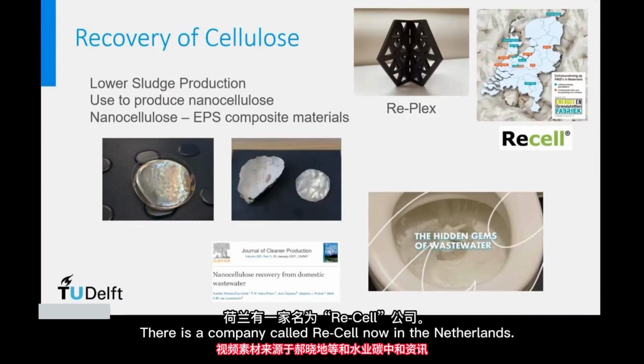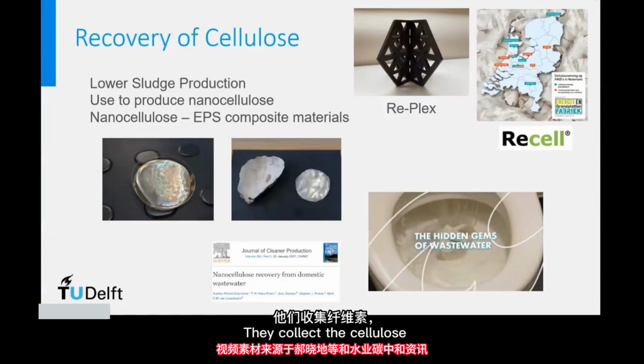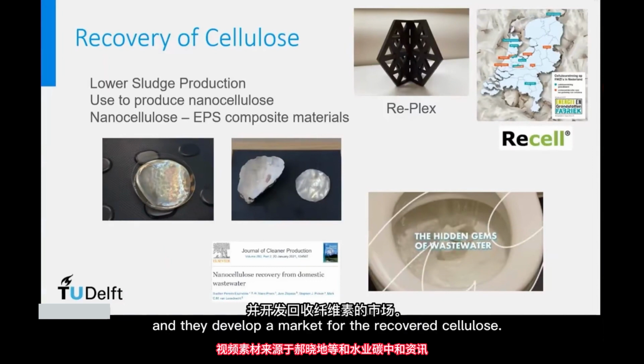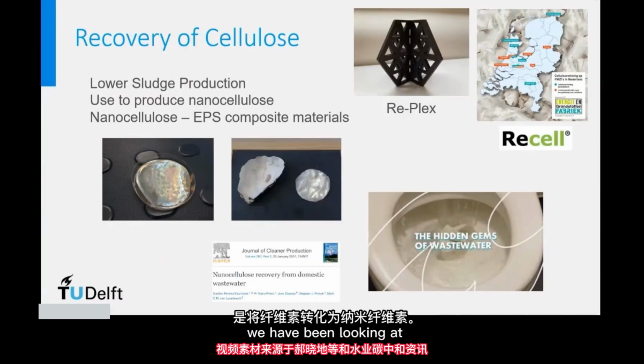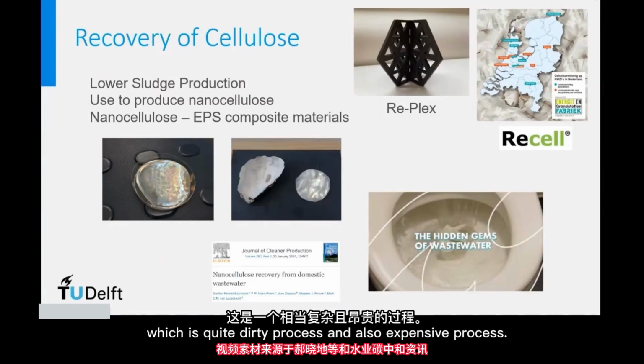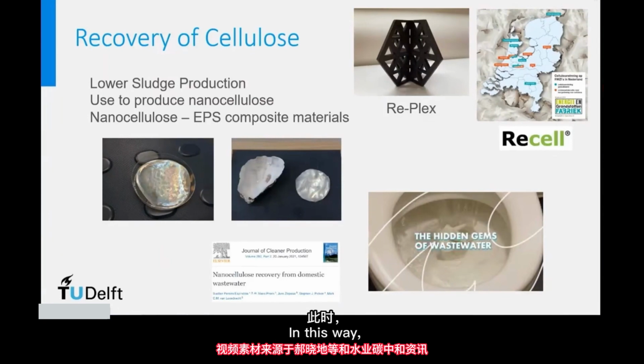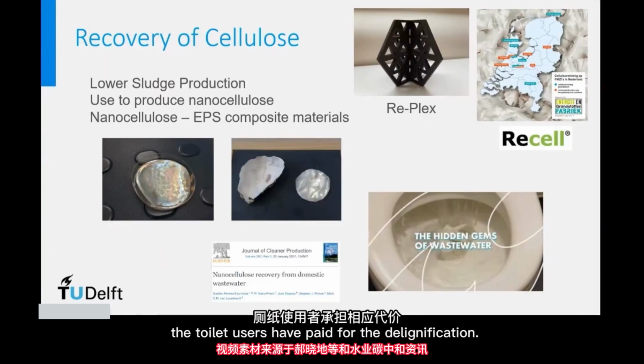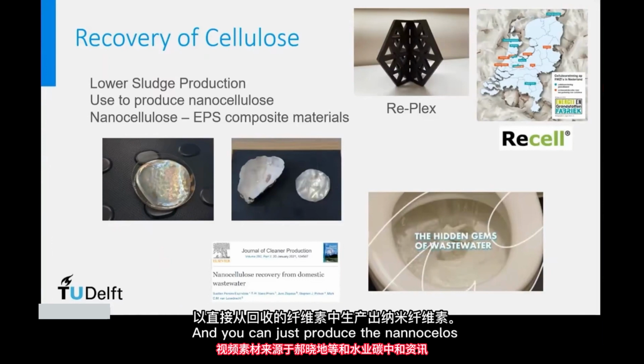There's a company called Recell now in the Netherlands. They collect this cellulose and they develop a market for the recovered cellulose. Now, one of the aspects we have been looking at is converting that cellulose into nanocellulose, because if you want to produce nanocellulose, you first have to delignify the cellulose, which is quite a dirty process and also an expensive process. And in this way, the toilet users have paid for the delignification, and you can just produce the nanocellulose right away from the recovered cellulose.